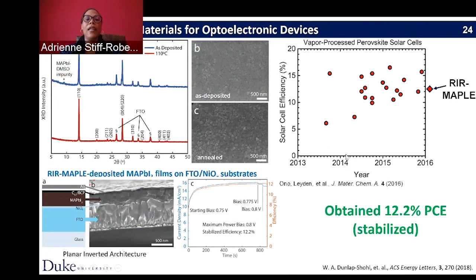So just as a demonstration, and this is all work done in collaboration with David Mitzi at Duke University, we've shown solar cells made by the MAPLE process. So you can see the morphology from an SEM image that's very typical from what you would get from spin coating these, as well as the X-ray diffraction patterns that demonstrate the presence of this crystal. So we made a device heterostructure for a solar cell where just the active region of the hybrid perovskite was deposited by MAPLE, and we made solar cells.